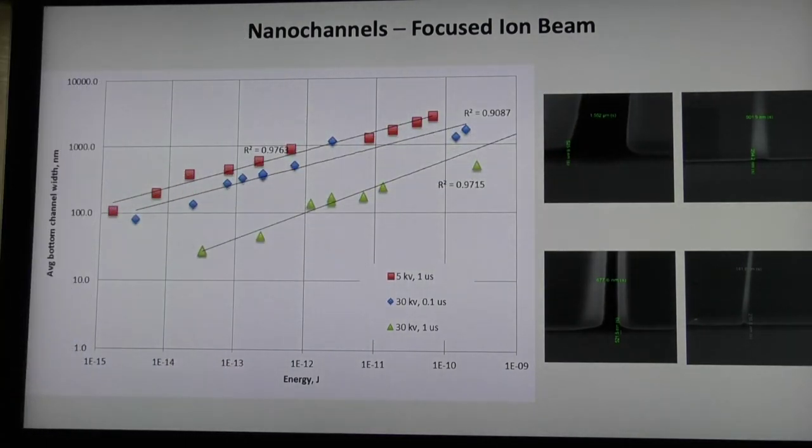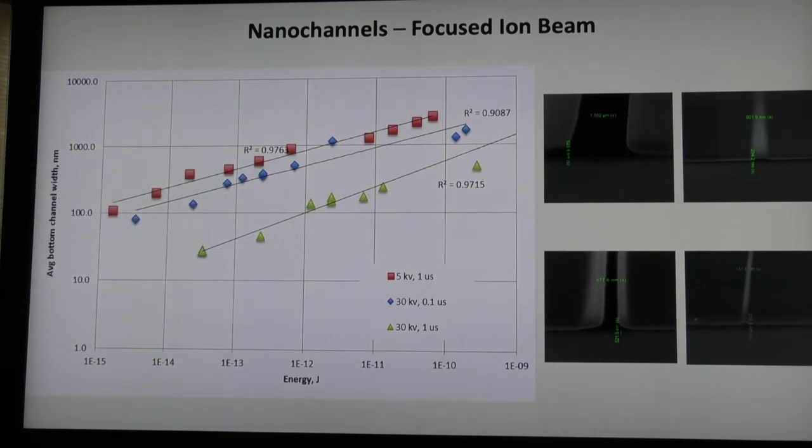And we experimented with the properties, the geometries of these channels, in particular the width, as a function of the energy of the beam that was used to create the channels. We were able to go to submicron, about 500, 400, 200 nanometer type scale, but that's the extent of it.